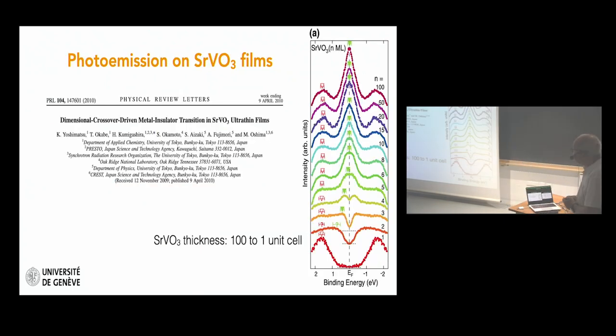And there is this beautiful experiment which was realized on strontium vanadate films. Strontium vanadate is a cubic metal. And you see here ARPES photoemission, where you see the spectra for thick films, 100 unit cells, and going down in thickness down to the monolayer. And by doing so, changing the dimensionality, eventually the bandwidth of the system, you see that you have a picture which resembles very much what I showed you before with the opening of a gap for these very, very thin layers.